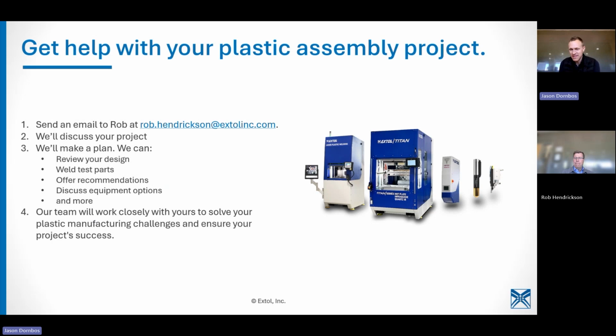Is there a minimum wall thickness needed? How deep does a weld go into a part? Great question. We actually were having this discussion with another customer yesterday about how big of a weld rib we need to add to this part so we can weld it. And I said 3 millimeters on both sides, so top and bottom. You'd need 3 millimeters each. And then our lab manager said 2, and then he said, well, maybe 2 or 3 millimeters. He was just trying to offer. But basically, 3 millimeters, close to 1/8 of an inch. That's about the size that you would need.